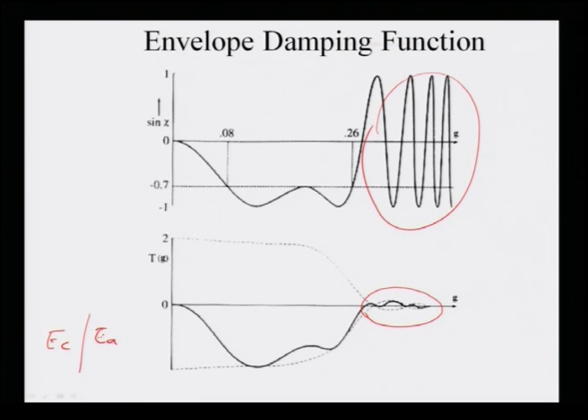Whatever the situation, as you can clearly see, there are zeros at higher values than G1, but beyond that the values of the transfer function are very small. Whether this can actually affect the resolution or the information in the microscope needs to be analyzed, and it has been seen that it can affect. So although the resolution limit will be given by the first crossover, the information limit can be higher. The information limit can be given by this point G2, which is at a higher spatial frequency.